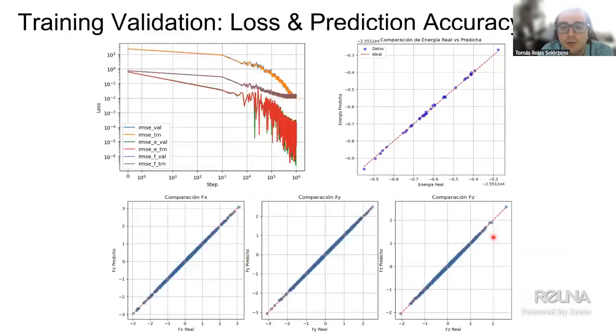We are now obtaining very good and very promising results, even with very small cells, we are able to minimize the loss function, or the error, based on the energies and forces predicted for the systems. And as we can see here, we can map the predicted energy from the algorithm to the energy calculated by the AIMD, and the same for the forces. We are able to use this software package to produce a model that can very accurately predict the forces of the interactions between one molecule and the nearby ones, and the energies that will cost.